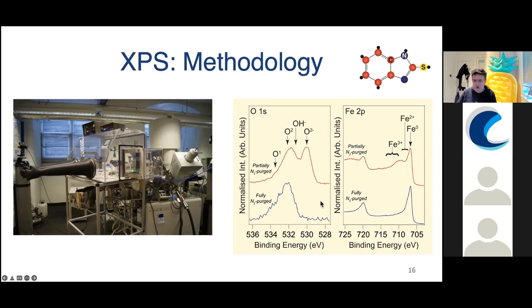And that's also shown in these oxygen peaks here, where we still see oxides if we're not fully purged, and we don't see those peaks when it is fully purged. So that's an important point. This methodology has been really important for us to get really into the details of these interfaces.